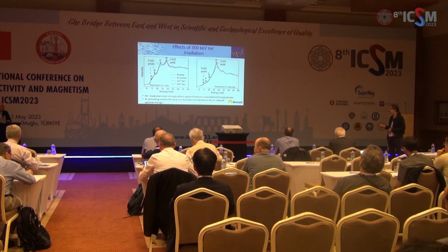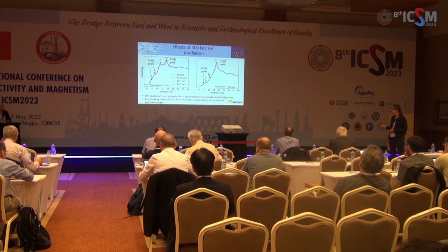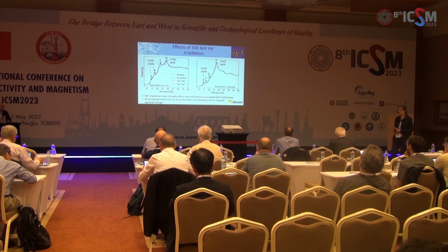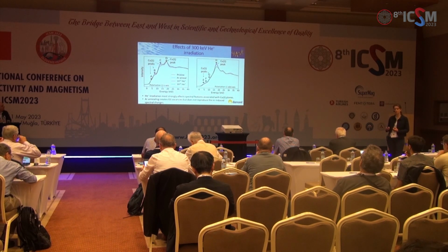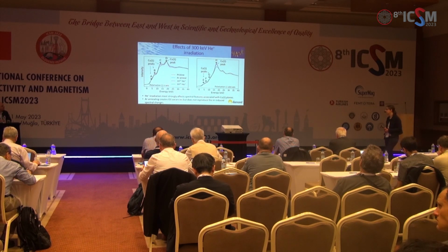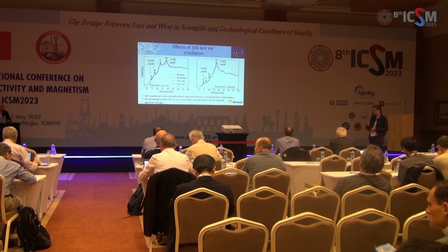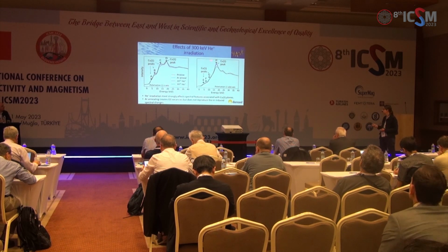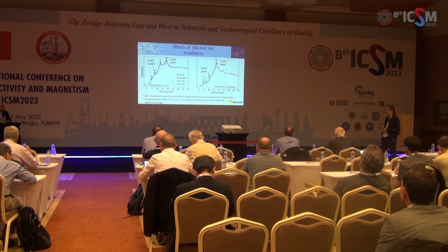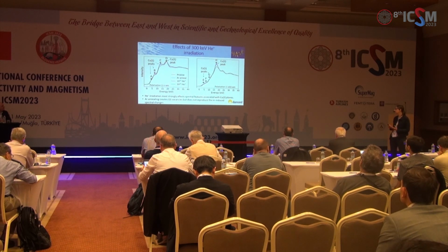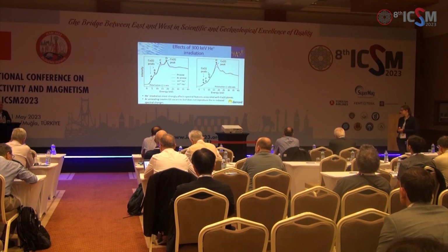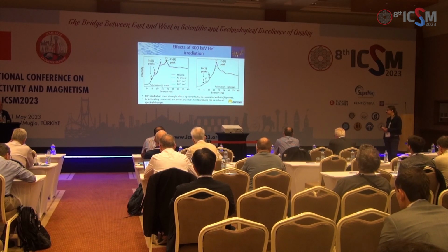So if we look at the differences, we're seeing them in these peaks along the rising edge. And that suggests that these are effects that are happening to the copper 2. So things are happening around the copper planes, within the copper planes, on irradiation, so defects around there. This peak also decreases a lot, and that's mainly due to copper 2 as well. So our first conclusion really is that this irradiation is causing defects in the copper 2 planes. It might be causing defects in copper 1 as well, but we've definitely seen them in copper 2.